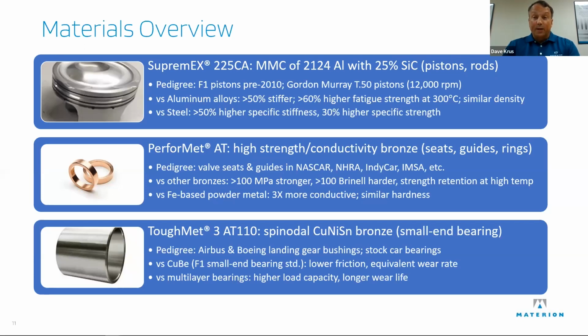So compared to aluminum alloys, it's a whole heck of a lot stiffer. It's got 60% higher fatigue strength at temperature, which allows a lot of design changes to a piston. And it's about the same density. It's also got a lower coefficient of thermal expansion, so the starting clearances can be a lot tighter. You don't have to worry about it expanding out, say, into a bore. Versus steel, its specific stiffness, so that's the stiffness divided by the density, is 50% higher than steel. You can theoretically make a component to do the same job as steel, be half the weight, and 30% specific strength.